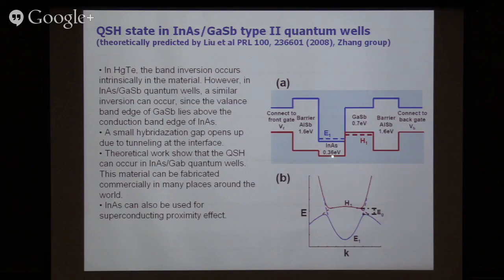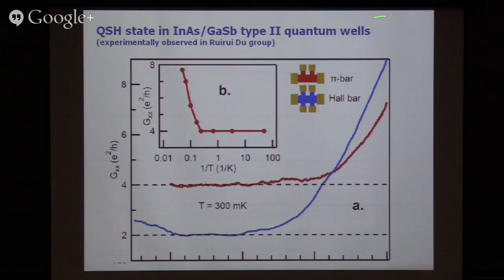But interestingly, when you put them together, at the interface an interesting fact happens. Namely, the bottom of the conduction band of one material sinks below the top of the valence band of the other material. So even though each material is not inverted, there's a relative band inversion. And we predicted in 2008 that the combined material will also become a 2D topological insulator. There is also another interesting desired effect, because out of all semiconductors, indium arsenide has the best coupling with superconductivity, and that's very highly desired in most applications. And only last year, a group actually confirmed that theoretical prediction, that in this material they also see a well-defined topological state.